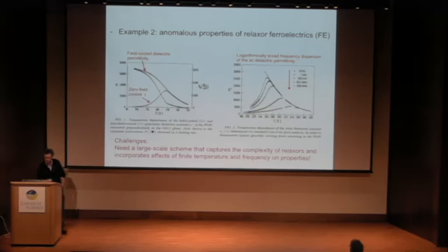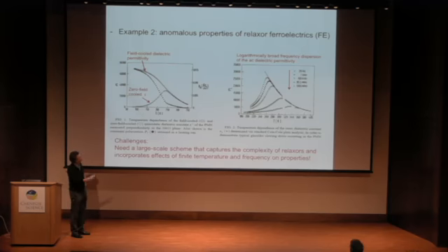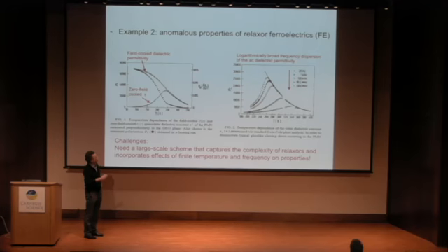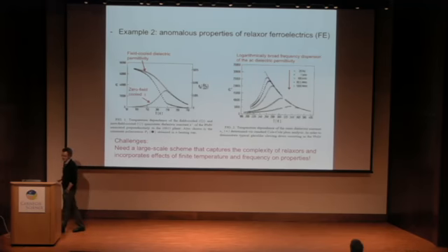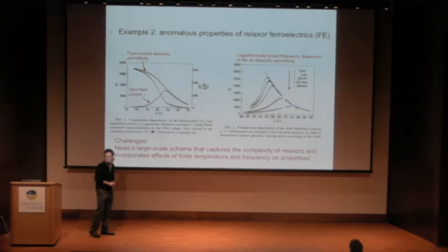But there is something that I've been extremely fascinated by since I saw it the first time in 1998, and this is the dielectric relaxation. So what it is: if you look at the real part of the dielectric response versus temperature, it really depends on the frequency of the applied field. You see the peak is going towards higher temperature as you increase this frequency. So imagine that we have a dream. We want to mimic, with atomistic simulations, this dielectric relaxation.